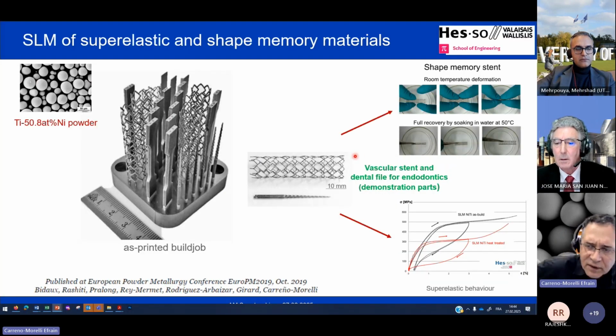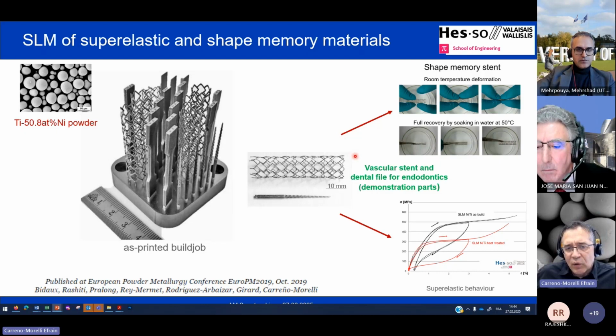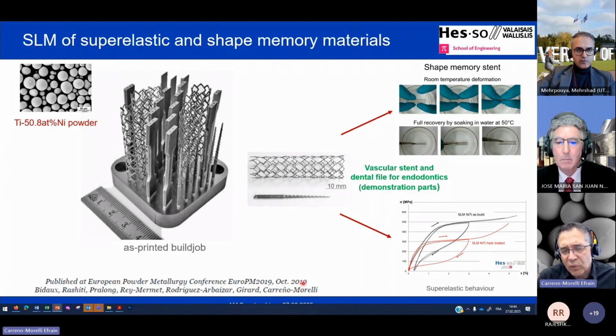I will just shift to some results on selective laser melting. We started to work with that in 2019. We use this powder, titanium 50.8% atomic nickel.